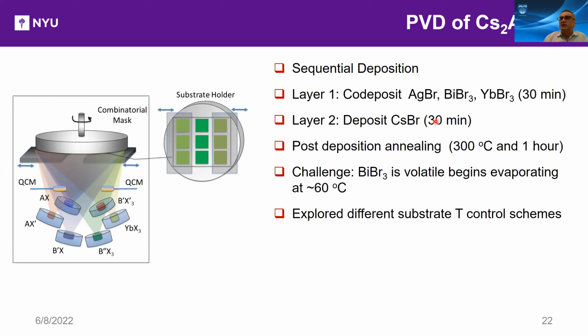The challenge with this one is that bismuth bromide is volatile. It begins evaporating at 60 degrees centigrade. So if you have the substrate temperature at anything above 60 degrees centigrade, not all bismuth bromide landing will actually remain there before reacting. It might actually re-evaporate.